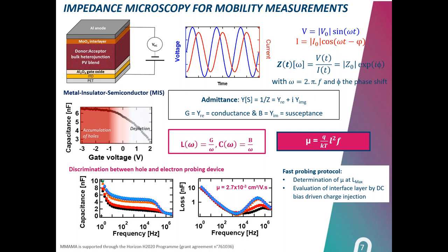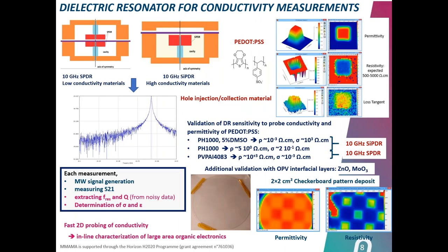So this is a powerful tool, not only to measure and determine the electrical properties of materials, but also to detect any problem in the process. Similarly, and as presented before by QWED, dielectric resonators were shown to be suitable for the characterization of similar materials. And you have an example here with PEDOT:PSS, which is traditionally used as a hole collection layer in OPV.